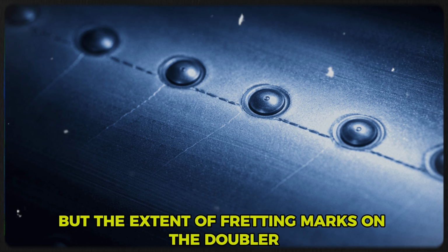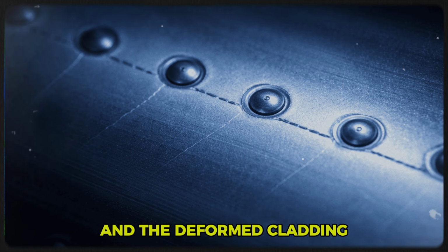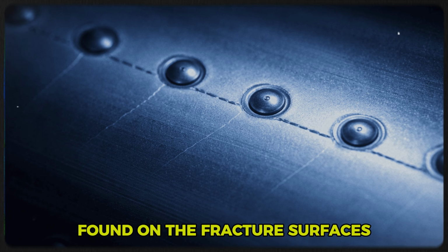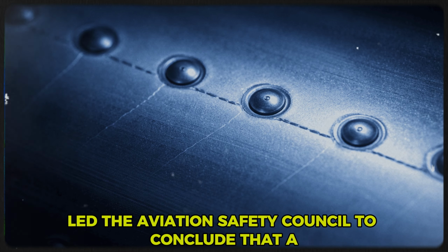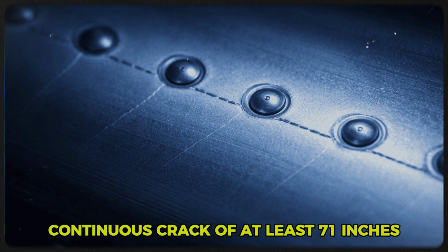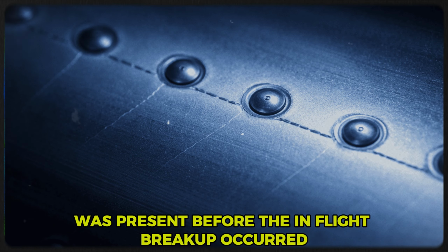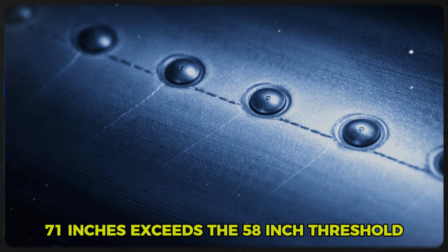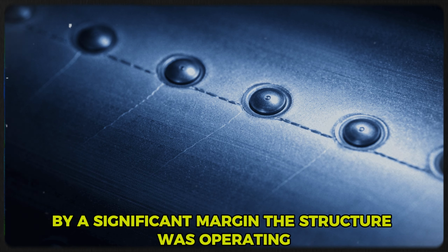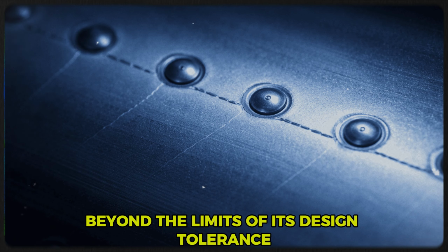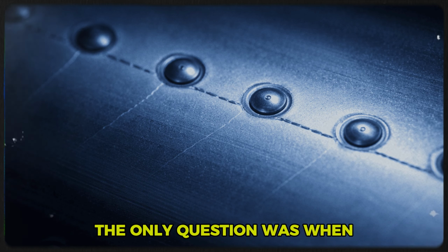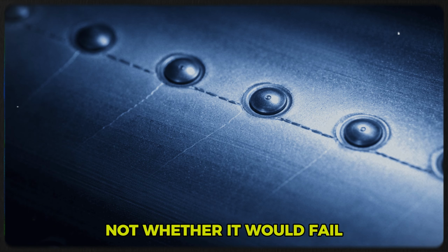The investigators could not determine the exact length of the crack before the accident flight. But the extent of fretting marks on the doubler and the deformed cladding found on the fracture surfaces led the Aviation Safety Council to conclude that a continuous crack of at least 71 inches, nearly 6 feet, was present before the in-flight breakup occurred. 71 inches exceeds the 58-inch threshold by a significant margin. The structure was operating beyond the limits of its design tolerance. The only question was when, not whether, it would fail.